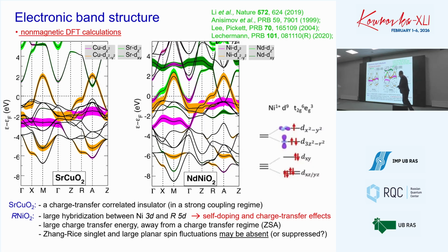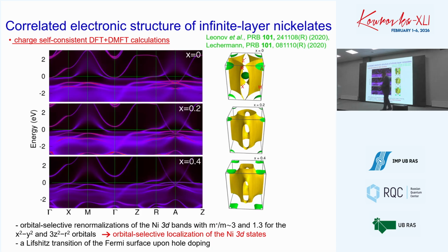In the beginning, people claimed in the first paper that there are no Zhang-Rice singlet states in the spectroscopic properties, and possibly spin fluctuations are not so important, but these were the first claims. I would say the present understanding is that these materials are in fact much closer to cuprates. They appear somehow in between cuprates and iron-based superconductors because of the multi-orbital Fermi surface. They resemble, in some sense, iron-based superconductors. In terms of renormalizations and strong correlations, they are more similar to cuprates.